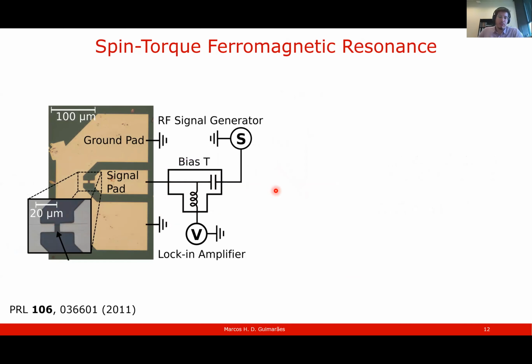One important method that was developed is a resonant method, which uses ferromagnetic resonance to read the torques. This is called spin torque ferromagnetic resonance. Here we apply an RF current, a current in the gigahertz range, which passes through a signal pad, and the connection between the signal pad and the ground pad is a stack that could be, for example, platinum and a ferromagnet like permalloy.